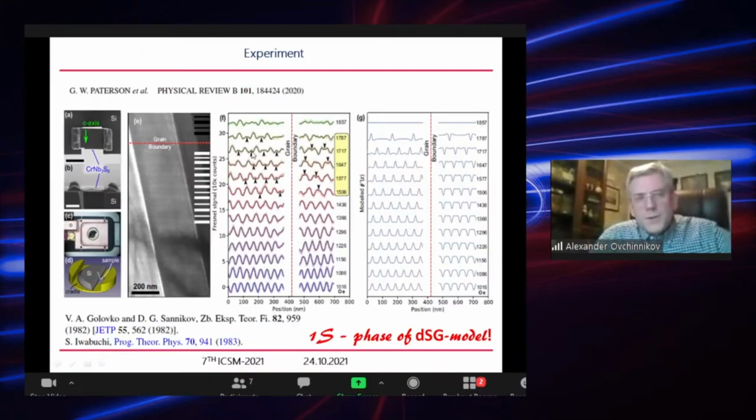If we analyze the profiles of intensity, we may notice also the appearance of additional peaks, shown here by black arrows. Very interesting, though not directly related to our topic: the sample splits into domains of different chirality, and the boundary between the grains of different chirality is distinctly seen in the experiment as an inversion of the profile.